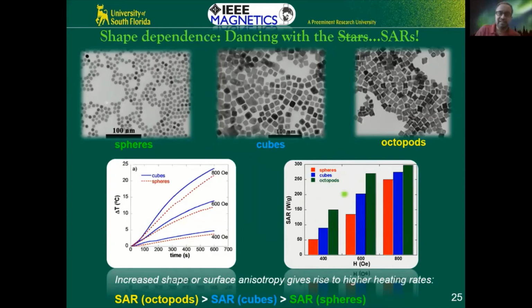And look at this data right here, the histogram. The comparison of the SAR values for spheres, cubes, octopods. There is no question here. It's very clear that as you increase the effective anisotropy, in this case the surfaces, you get a higher SAR. It's one of the most important results that came out from our group a few years back, when people were not really looking at it, not paying attention to this. And we were the first group that pointed out the importance of anisotropy. And now I think many groups are trying to make sure that they look at the shape anisotropy and the effects of this on the SAR. So this is one of the first results that came out.